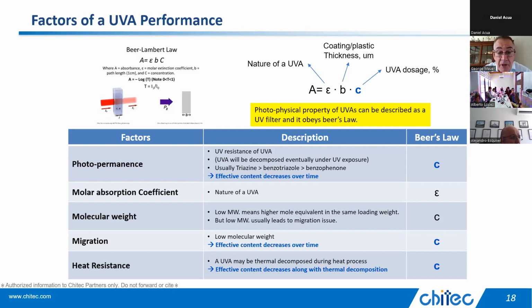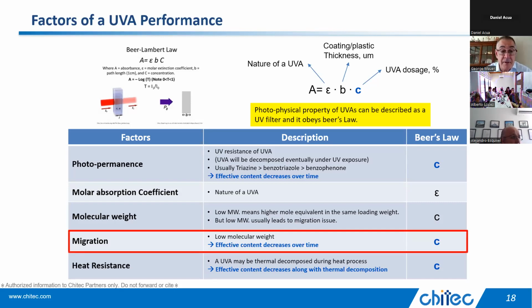Migration is one of the things that people don't think about enough. And the migration is a big deal. Something like 1130 migrates very quickly, especially with water, car wash, soap. And when it does that, it's no longer working for you because it's gone. The smaller molecules, Tinuvin 328 was used for decades. And the only reason that was kind of okay was people would put in a lot of it. So it had a good molar absorptivity coefficient. So when you loaded it up with 3%, you could afford to lose a percent a year and still get some performance. Although eventually at 5 years or so, it would go away.